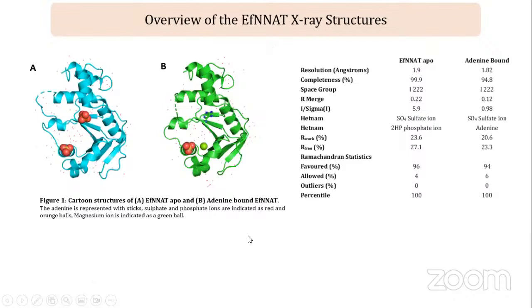So interestingly, this is the first crystal structure to be solved for this protein, and it was solved at a very high resolution, as indicated in the table. As we can see, the APO form was resolved at a resolution of 1.9, and the adenine bound form at a resolution of 1.82 angstroms. So these are the two structures that have been deposited so far in the protein data bank.